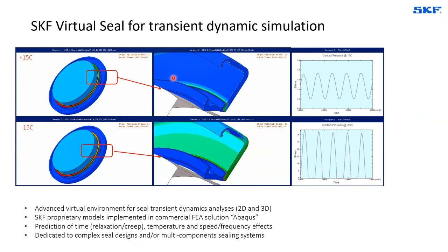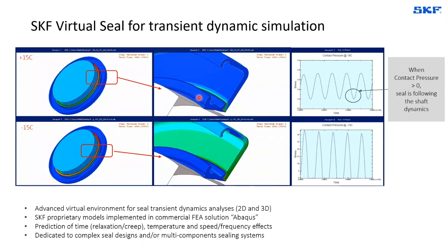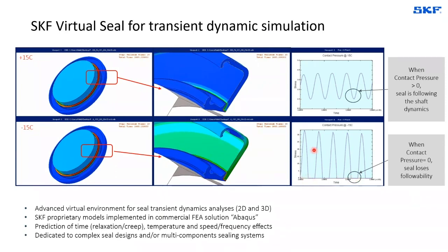And we can see, back to the ball example of Galileo earlier, that for a temperature of 15 degrees centigrade, we didn't see that. Despite the dynamic runout in place, the contact pressure is above the zero line, telling us that the seal remains in contact, as we can see in this picture. However, as the temperature is reduced to minus 15 degrees centigrade, suddenly we see an area where the contact pressure drops to zero with a certain period, telling us that there are times over the rotation where the seal is losing contact with the shaft. This, of course, is important for us, as this can lead to tremendous issues in application, which we will see in the course of this presentation.